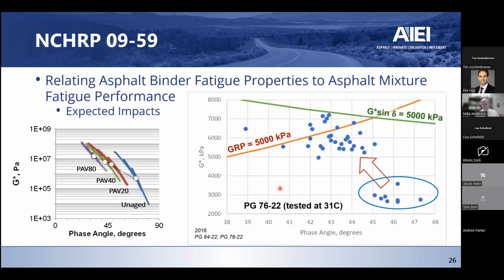So these are some 64-22s, 76-22s that we tested in our lab back in 2016. We plotted this to take a look at what G* versus phase angle looks like for these materials, and how they compare with the specification. First things first, if you take this orange line out for now, just ignore the orange line. Everything in 2016 had to be at or below that green line. Anything above that would fail G* sine delta of 5,000. So all this data meets the AASHTO M320 from back in 2016.